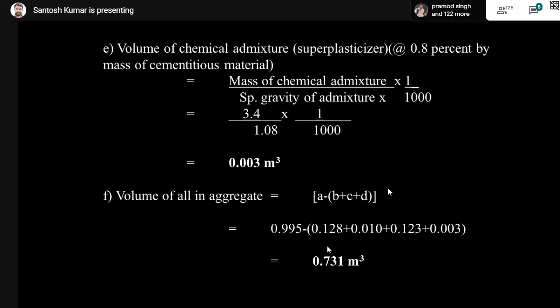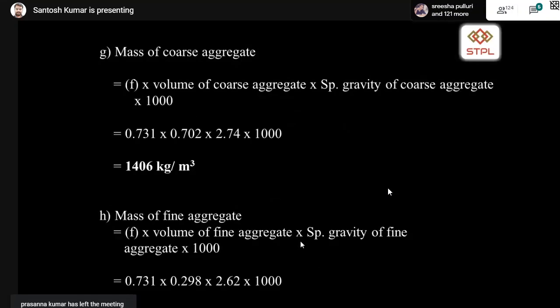And the volume of all-in aggregate is calculated by the absolute volume minus cement volume, microsilica volume, water volume, admixture volume. So in the absolute volume, if you remove cement, microsilica, water and chemical admixture, you are left with the volume of aggregates. This 0.731 cubic meter is the volume of all-in aggregates.